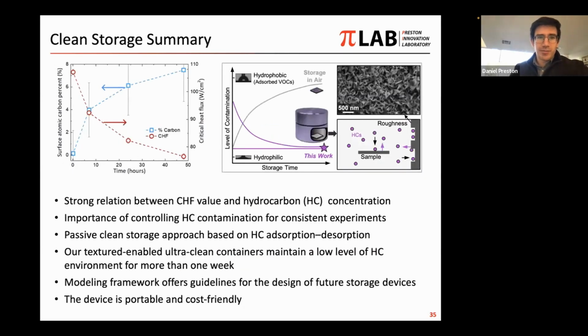And so in a nutshell, we basically saw this, first of all, strong relationship, as we mentioned, between the CHF and the hydrocarbon contamination or the concentration on the surface, which represents the importance of trying to understand and control contamination. And to address it, we developed this passive clean storage approach, which is based on basically a sacrificial container. It's a getter for contaminants using the high surface area and initially ultra clean state.